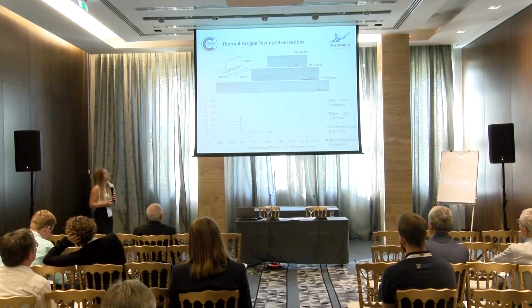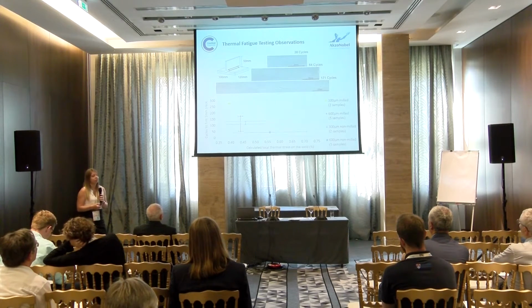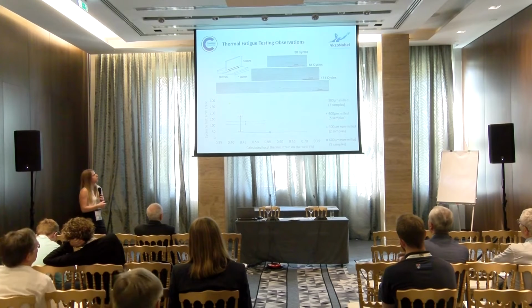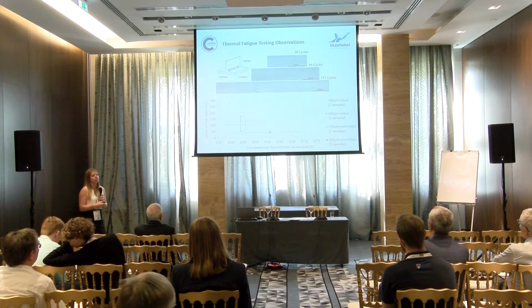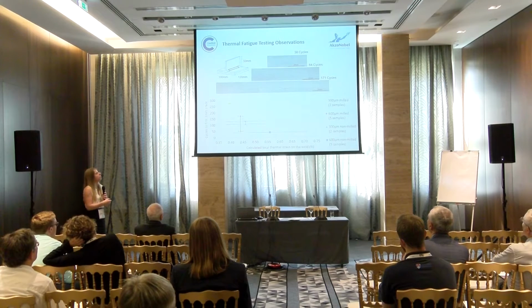So this is just some of the results from the thermal fatigue testing. Samples were removed at regular intervals and a handheld microscope used to investigate cracking behaviour. Images of the cracks were taken in order to measure crack length and determine crack growth rates. It was identified that cracks will initiate along the weld fillet area and will channel parallel to the weld length.